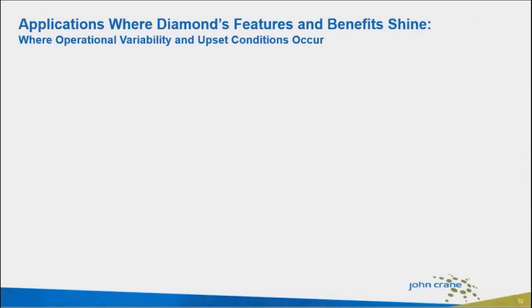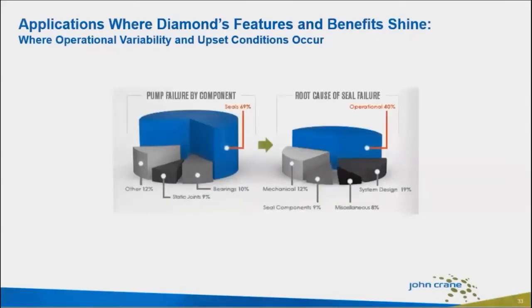So shown here on the slide is a graphic of market research completed, which shows pump failures by component. On the left side of the graphic, you will see that mechanical seals account for more than 2/3 of pump failures. And if you take a deeper dive on the right side of the graphic, you'll see that a substantial amount of these seal failures and pump failures stem from operational issues. These are often unscheduled events running the seal outside of the design envelope or from other unintended variations in the operations.